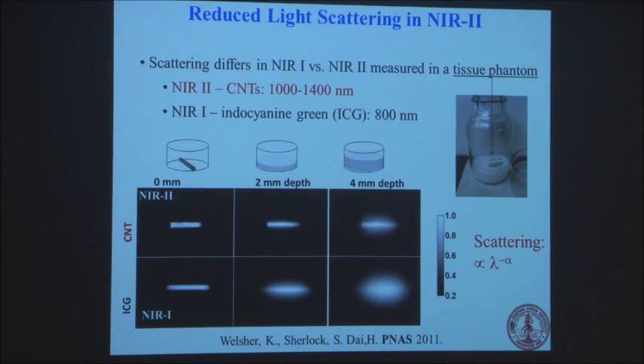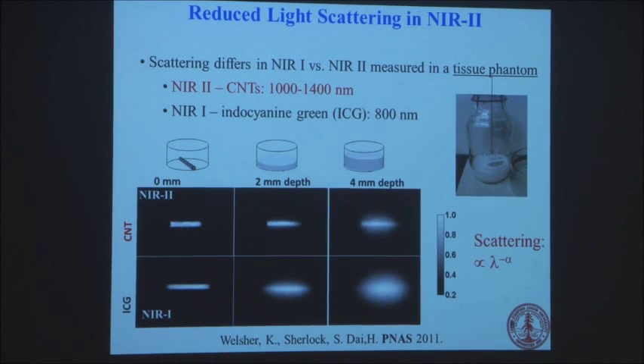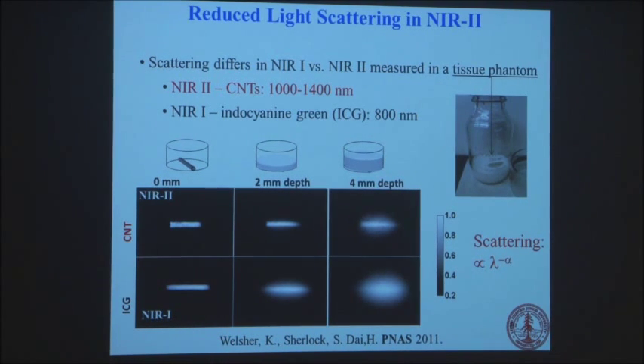But you see the smearing is not as bad as ICG, which is a molecule that emits at 800 nanometer, and that's the traditional near IR. At the shorter wavelength, 800 nanometer, the smearing is much, much worse, so that this object no longer looks like a line, because of scattering. So that right away tells you that you will be able to image things at higher resolution if you detect things at longer wavelength.